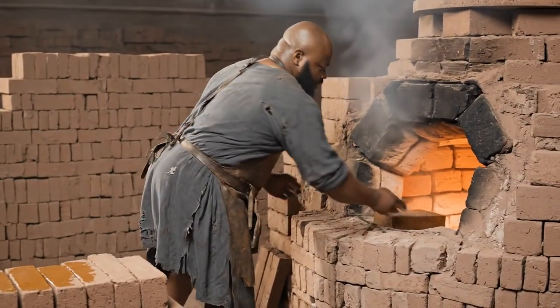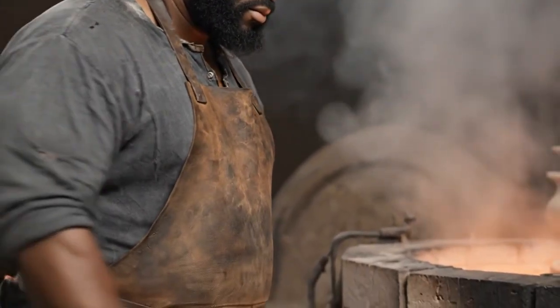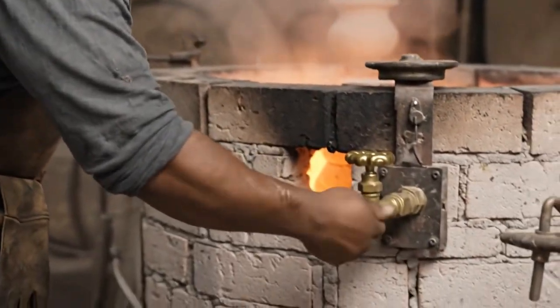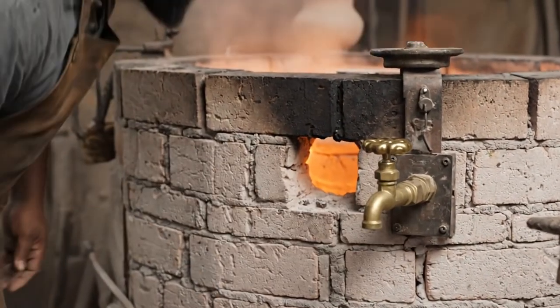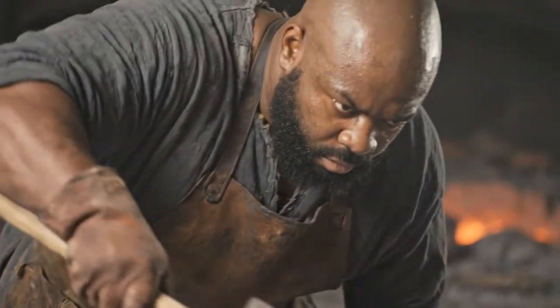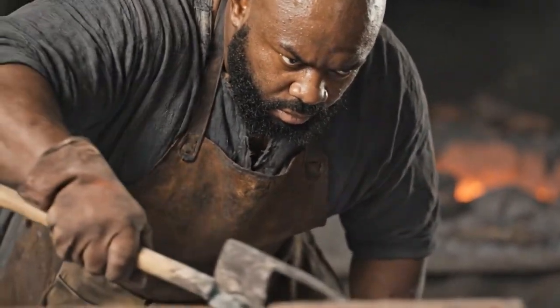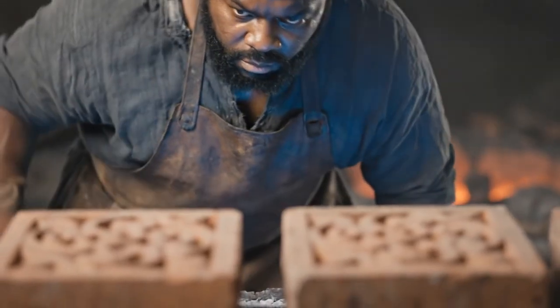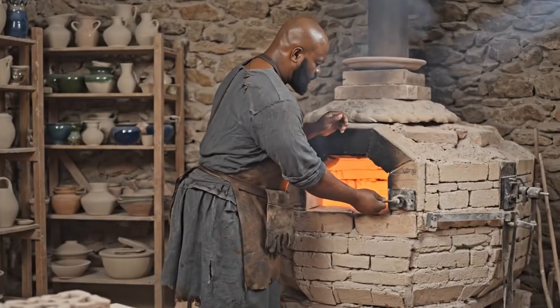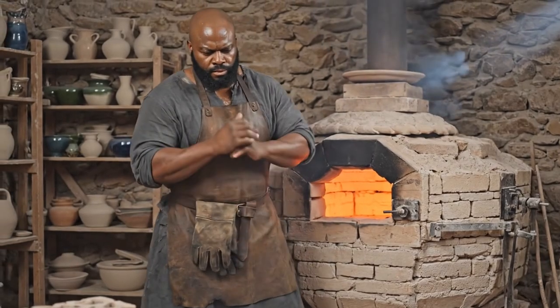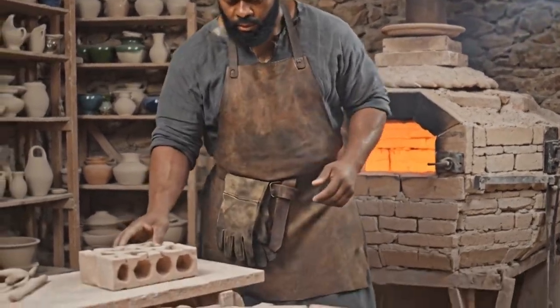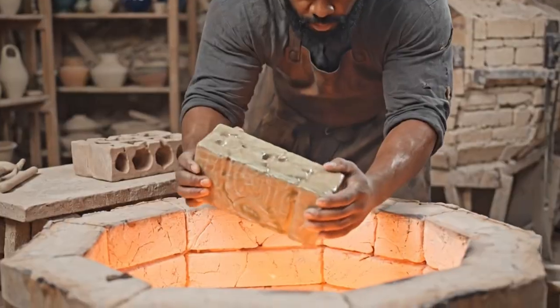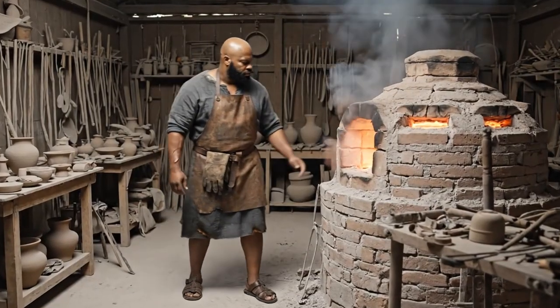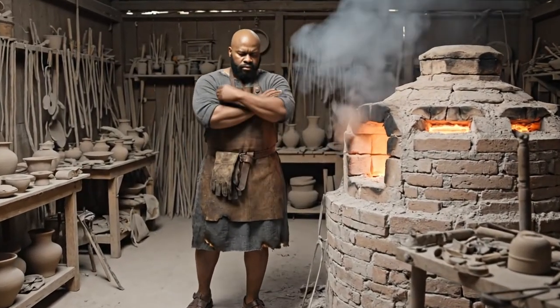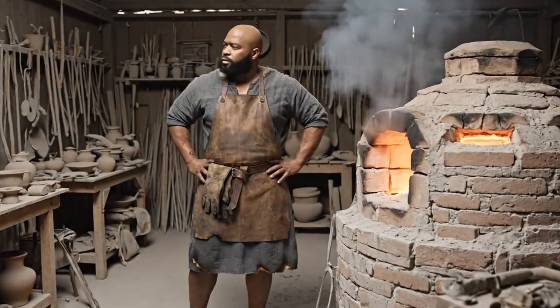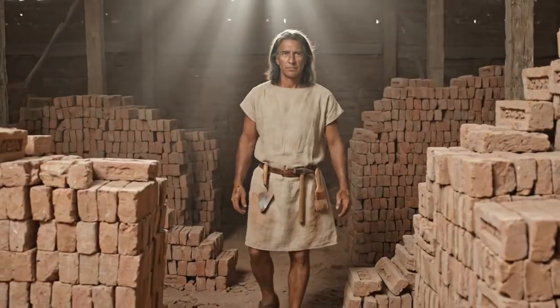The glazed bricks go back into the kilns for a second firing at lower temperature, around 800 degrees Celsius, just hot enough to melt the glaze into a glass-like surface, but not so hot that it runs off the vertical surfaces or changes color unpredictably. And this second firing is even more delicate than the first because temperature control is more critical and the margins for error are smaller. And a kiln full of glazed bricks represents such enormous value in materials and labor that a failed firing is a financial disaster.